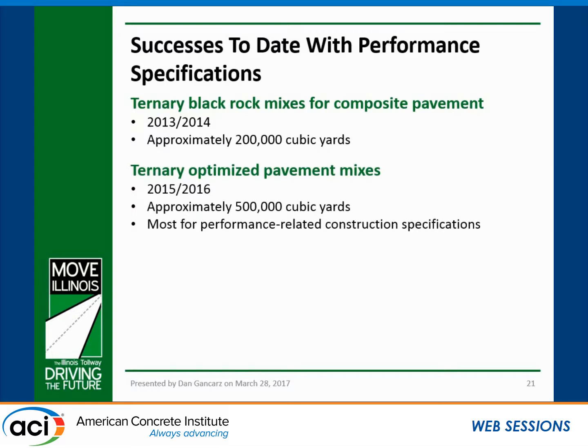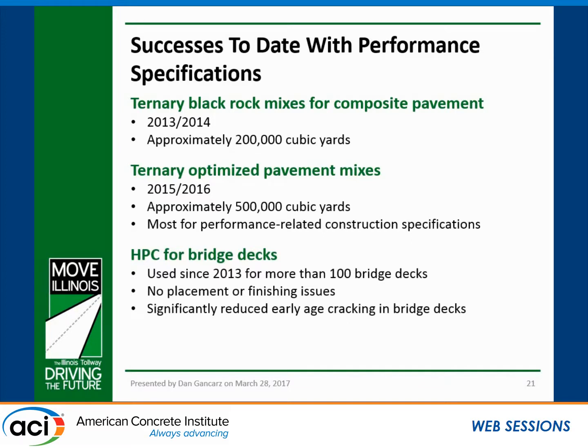2015 and 16 was the single lift ternary optimized, similar to the mix design I showed previously. That was approximately 500,000 cubic yards. Most were used for the performance related construction spec. And then HPC for bridge decks. Since 2013, we've placed over 100 bridge decks using the HPC spec. There's been no placement or finishing issues, and we've seen a significant reduction in early age cracking compared to the previous DOT mix that we were using in bridge decks.